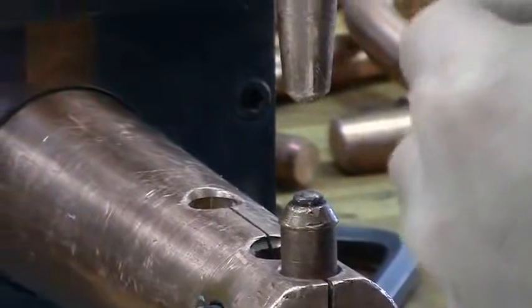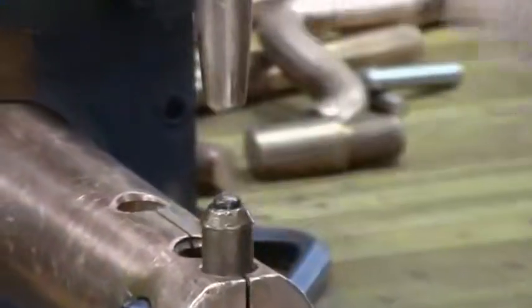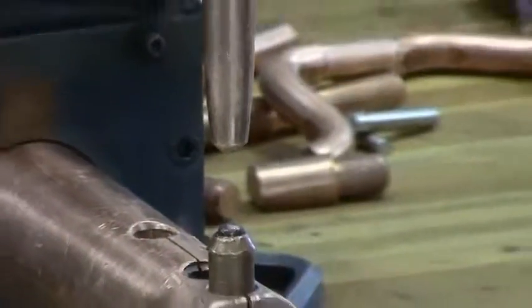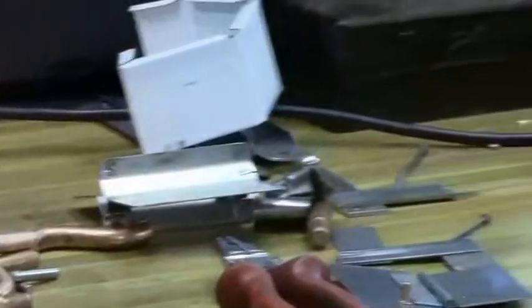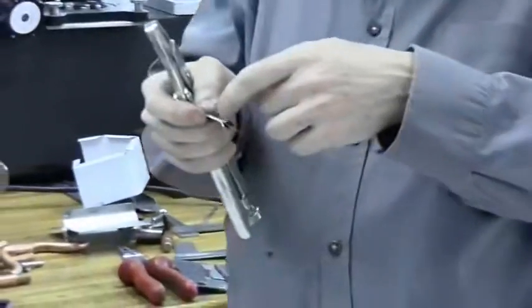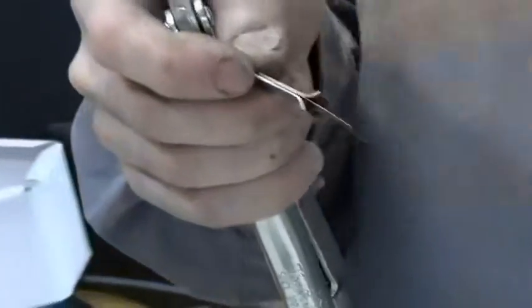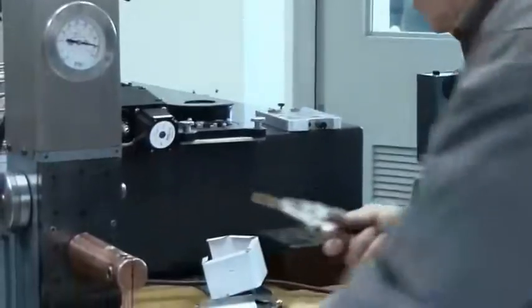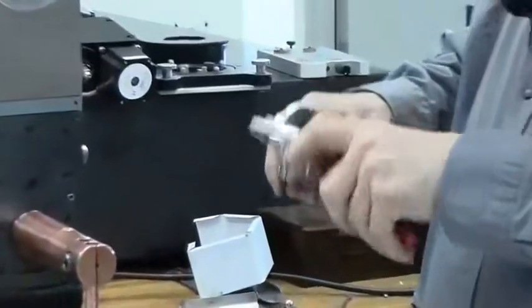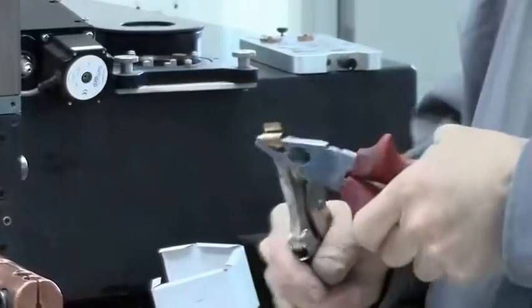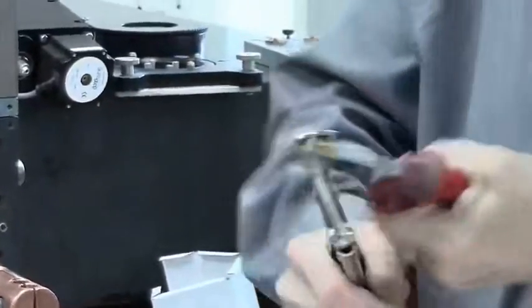The setting is more or less the same setting you would use, a bit higher than you would use if it was just stainless. So you trap the part. Okay, and now it's welded, and if you try to pull it out, it's actually very strong. I mean, there's some strange alloy formed in between, but you don't care. It's all melted through and becomes one piece, and it's strong enough. You can again do a test for strength, and it's very strong. You can't rip it out.